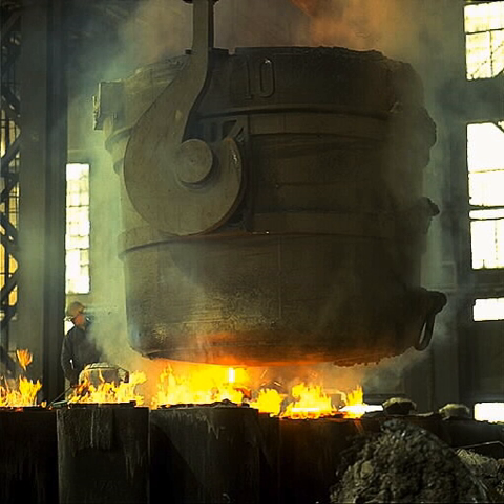These high chromium alloys attribute their superior hardness to the presence of chromium carbides. The main form of these carbides are the eutectic or primary M7C3 carbides, where M represents iron or chromium and can vary depending on the alloy's composition. The eutectic carbides form as bundles of hollow hexagonal rods and grow perpendicular to the hexagonal basal plane. The hardness of these carbides are within the range of 1500 to 1800 HV.